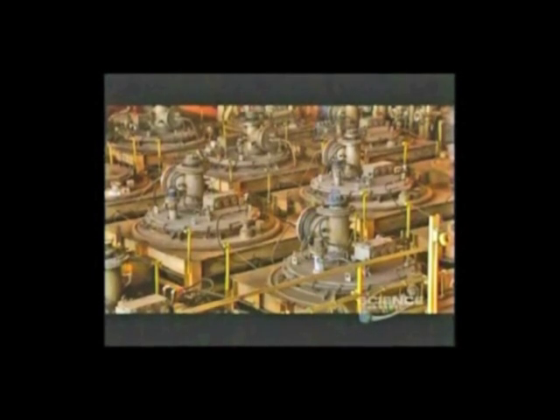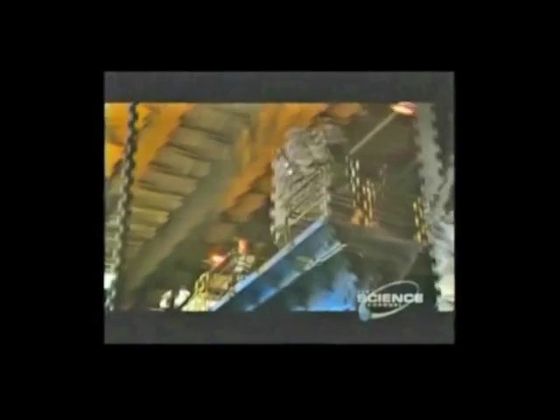As the titanium tetrachloride cools, it turns into a liquid, to which they add magnesium and heat it to 1500 degrees Fahrenheit for four days. The magnesium then reacts with the chlorine, and this separates the magnesium and the chlorine from the titanium. This liquid is then put into another furnace where a vacuum draws off the magnesium chloride. Pure titanium is then left behind as a sponge due to all of the holes of air in it.